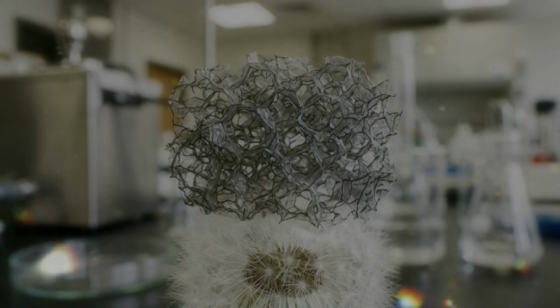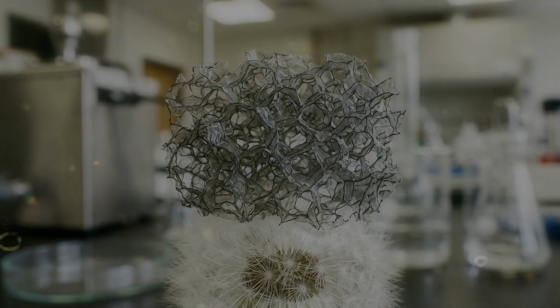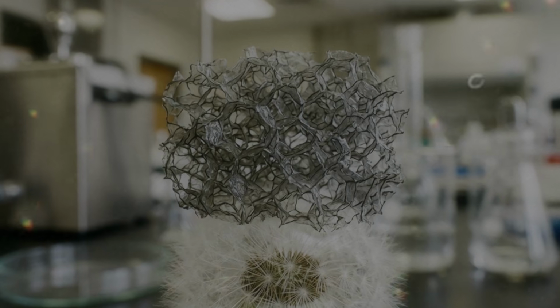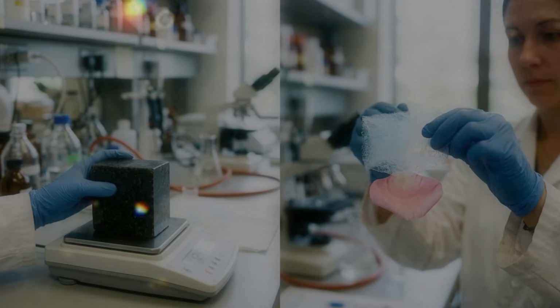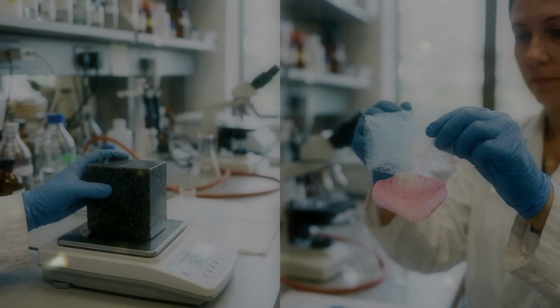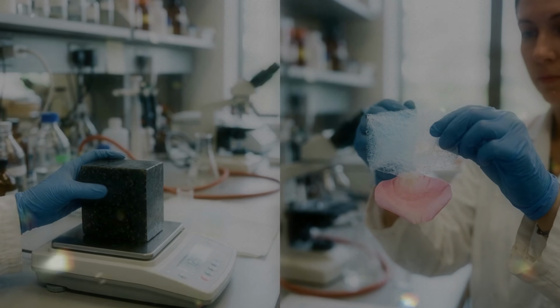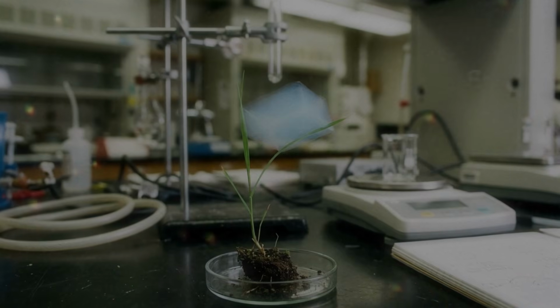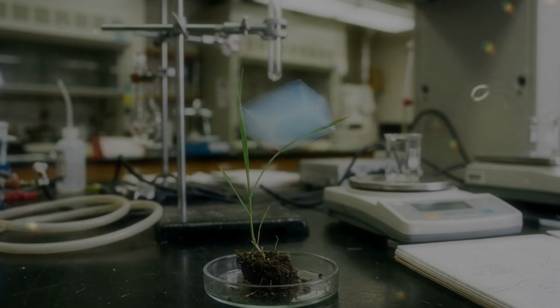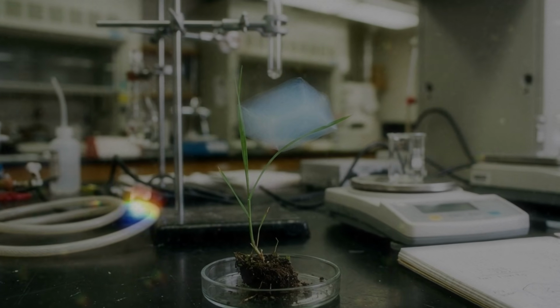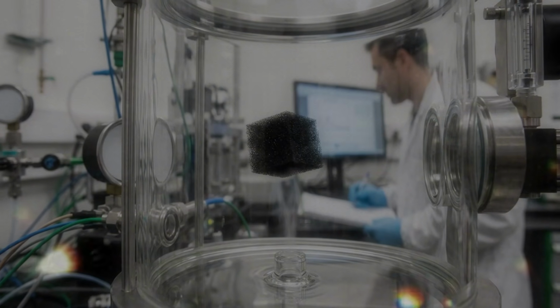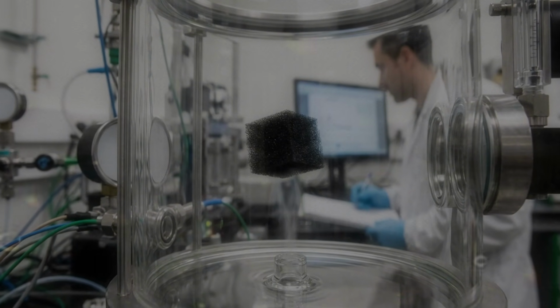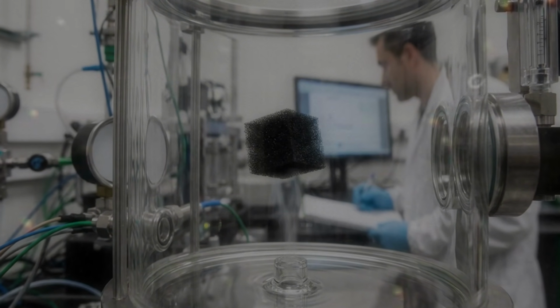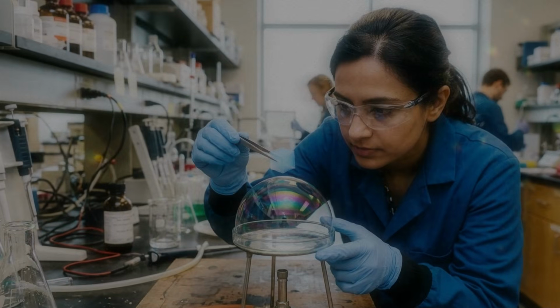If the liquid simply evaporates from an ordinary wet gel, the retreating surface of the liquid can pull on the tiny walls of the structure. The forces involved may shrink, bend, or collapse the pores. The result can still be a porous solid, but it may be denser and much smaller than the original gel. Aerogel production uses drying methods designed to reduce or avoid that collapse. We will follow that process more closely soon because it is one of the cleverest parts of the story.